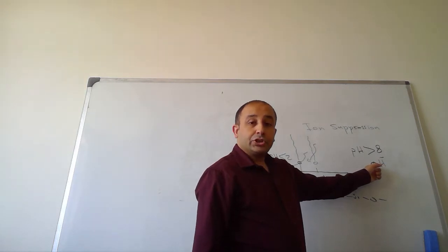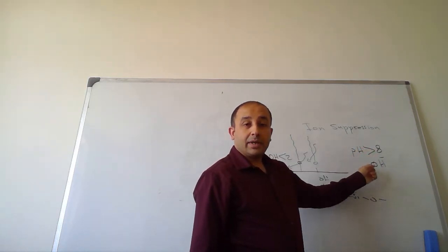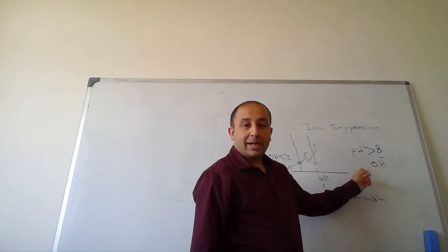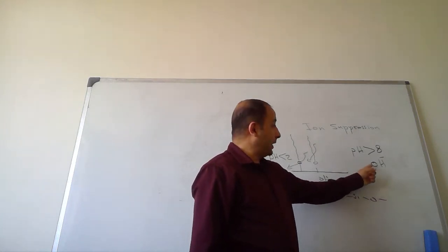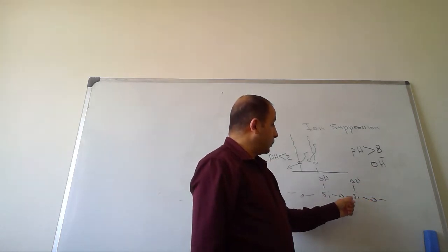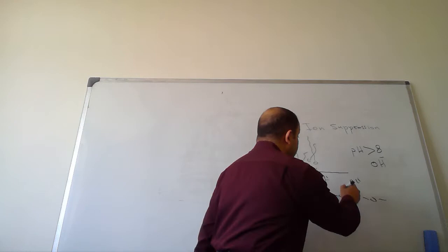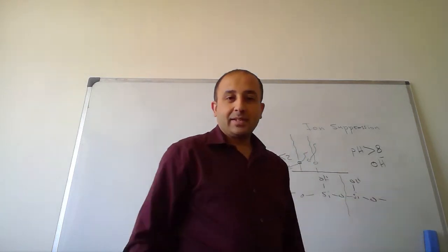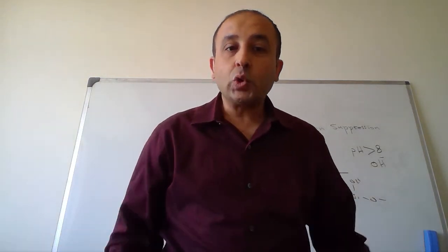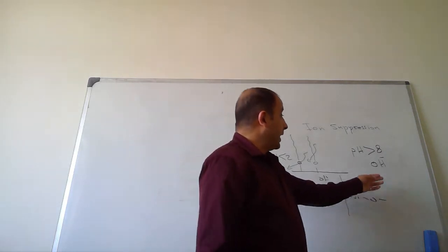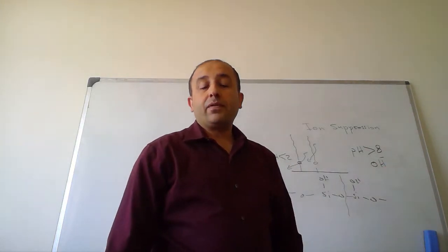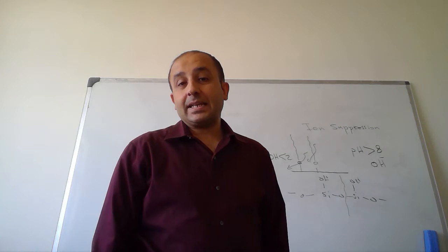if the pH of the mobile phase is above 8, we will have an abundant quantity of OH minus. Now, oxygen in OH minus here will react with silicon in the polymeric form. Now, silicon will be broken down to monomers. So we will dissolve the polymer to monomers due to what? The abundance of oxygen in basic medium.